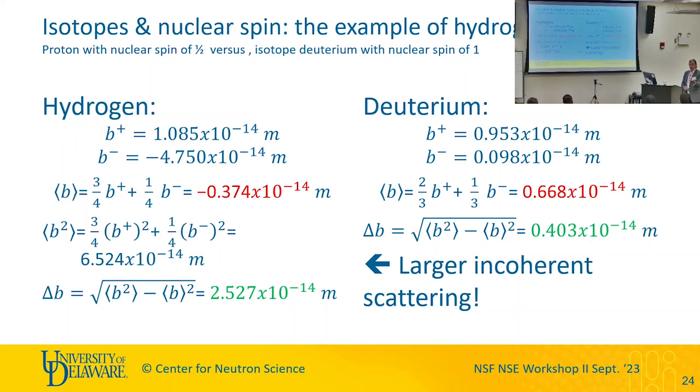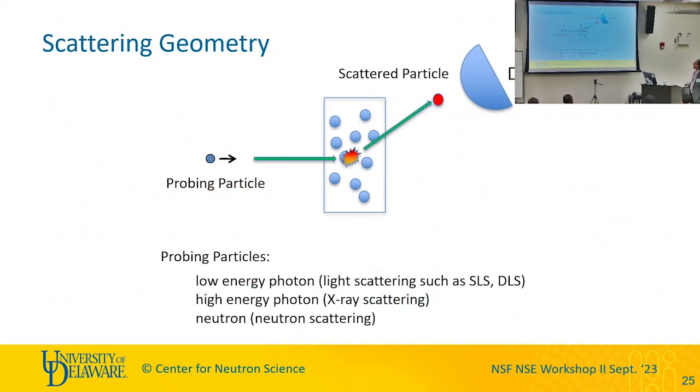So rather than deuterate a polymer and put it in H2O, we might use D2O, and use a hydrogenated polymer, because we have a lot less hydrogen in the system, since we have a lot more water in a dilute polymer system. Our background would be much lower. We get a much better signal to noise. So it's not equivalent sometimes, right? The amount of hydrogen you have in a system can raise your background, okay? Just something to keep in mind. Again, you're going to see this again. So I'm just introducing the concept, giving you a touchy-feely idea that there's something there.